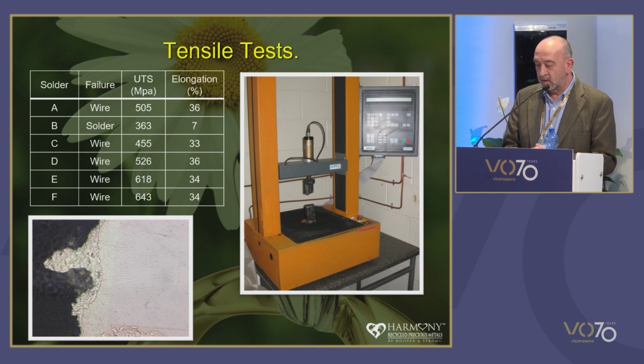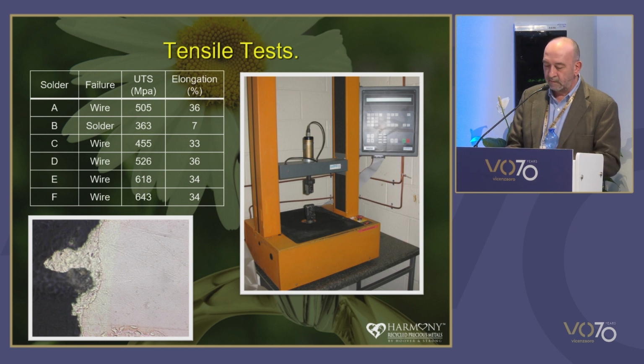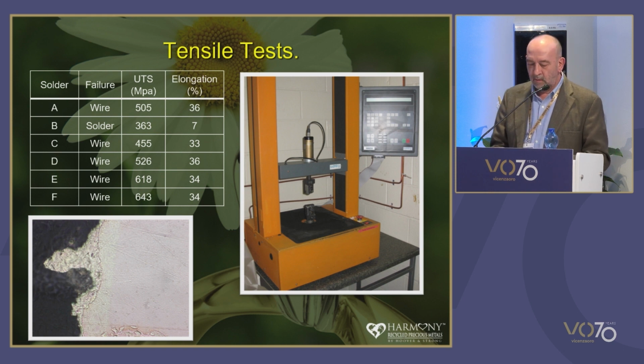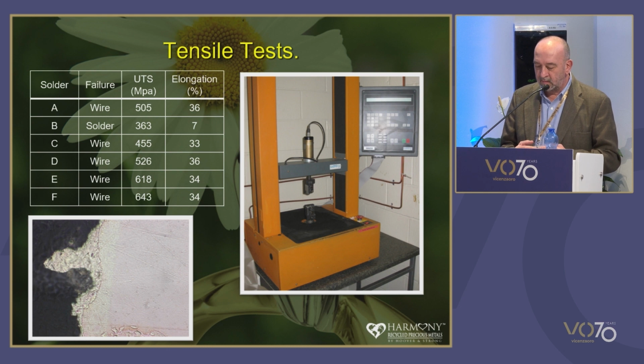If it fails in the solder joint, it doesn't necessarily mean the solder is not suitable for manufacturing, providing the breaking stress is high enough. Failure at the joint will either be because the parent metal solder bond is weak, or the solder itself is brittle and it has low elongation. So we took 1 millimeter diameter wire, we soldered them together using the torch method only for this test. It was a little bit difficult to do it in the furnace.